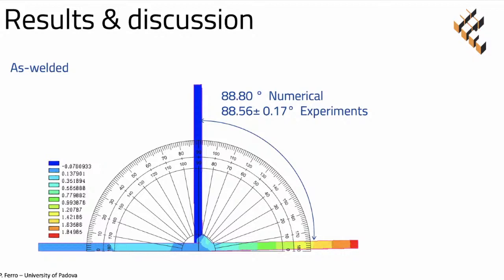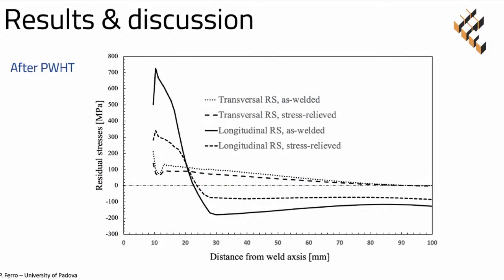It is important to say that we also calculated the angular distortion after the stress relief heat treatment, but we didn't find any change. So in both experiments, we didn't find a variation in angular distortion after the stress relief heat treatment.